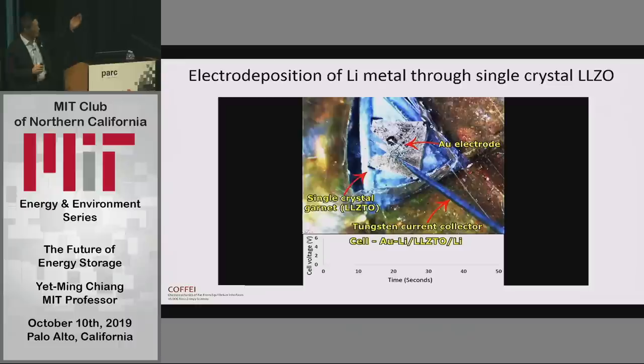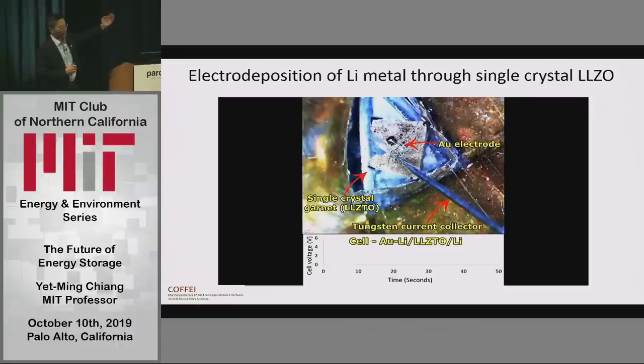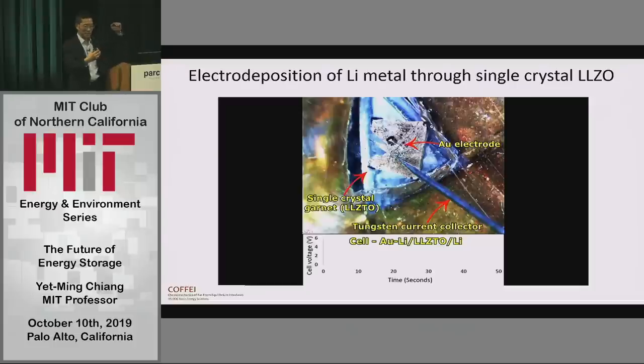Okay. So if it were working, what you would see, in this case, we're depositing lithium metal from the bottom up towards the top where it says gold electrode. And what this video would show you is that you see lithium metal growing up through the single crystal, and eventually at the bottom, you see the electrical short occur. Okay, so why does it do this?